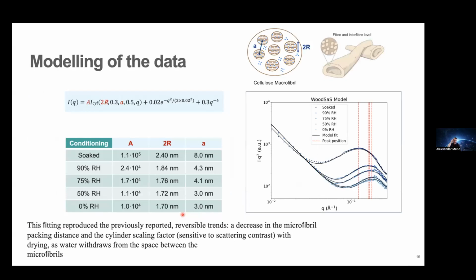And typically one of the difficult things, and here I think advice from, for instance, Linnea and Kim is really central, is how to now interpret your data, because a bump does not make anybody particularly happy. So in this case, the approach was to use a model in literature previously developed by others for cellulose macrofibril materials. And here you see just the mathematical expression for the model. To the right, you see how the model fits the data, so it fits reasonably well. And what you get out in this case from the model is what kind of changes I have in the fibril distance, and also whether I have a potential swelling of the actual fibrils.